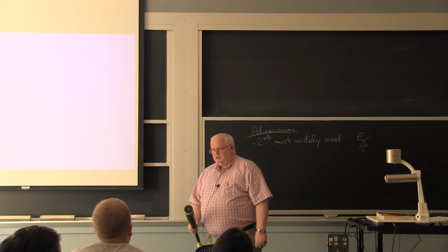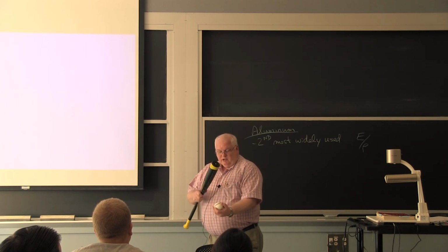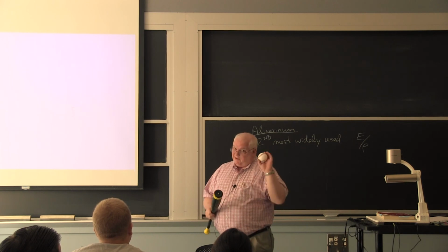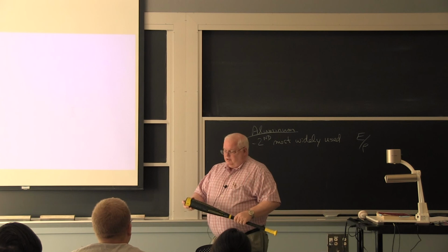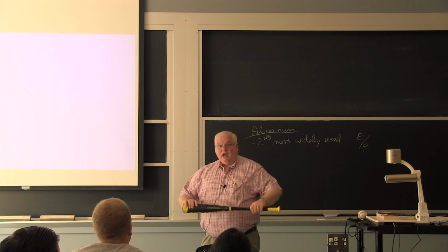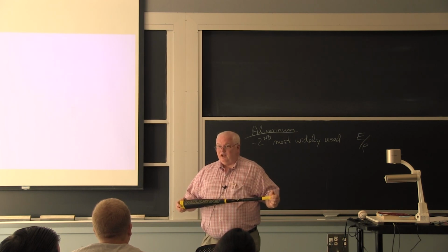The next week I actually got some balls and put them in a compression machine and measured their relative stiffness. It has a lot of hysteresis, which complicates things. But nonetheless, we may have taken an exemplar bat and pushed onto the bat and measured its stiffness, and lo and behold, they were the same within like 30 or 40%, okay?